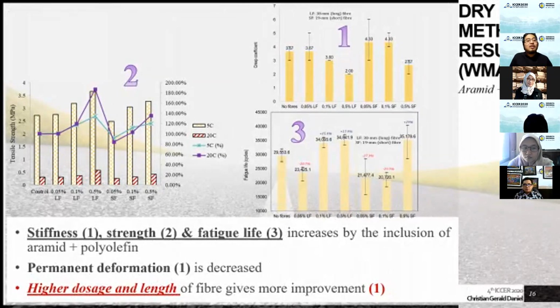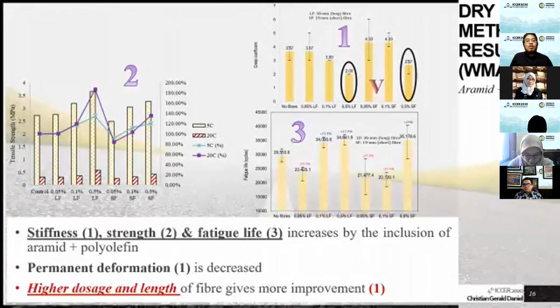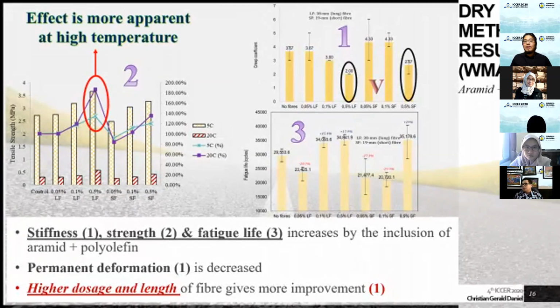And this is for hot mix asphalt. What about warm mix asphalt? We can see here also the stiffness, strength, and fatigue life increase. Permanent deformation is decreased, which also indicates the increase of stiffness. And the interesting phenomenon is that a high dosage indicates more improvement, and also the length of the fiber makes a significant contribution to the improvement. As we can see here, the longer fiber, which in this case was 38 millimeters in length, is more beneficial than the shorter one at the same dosage, which is 19 millimeters. Okay, and again, the effect is apparent at high temperature.